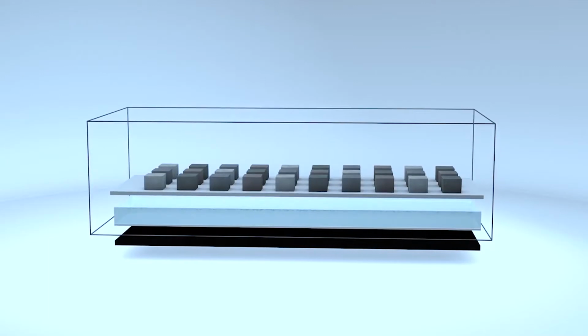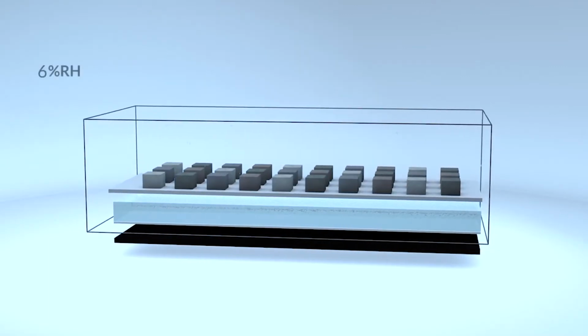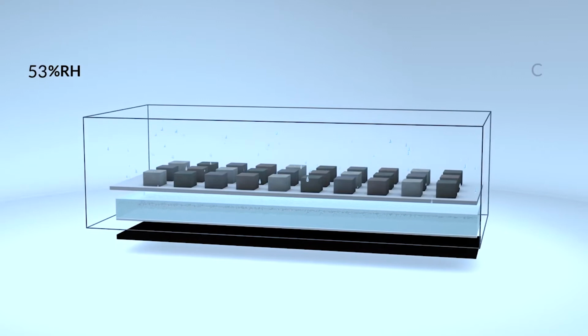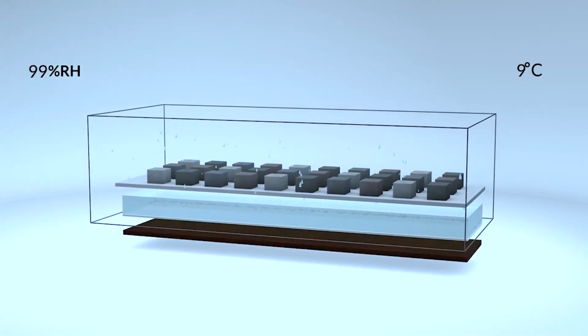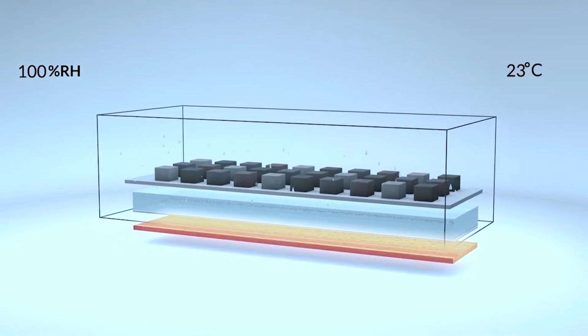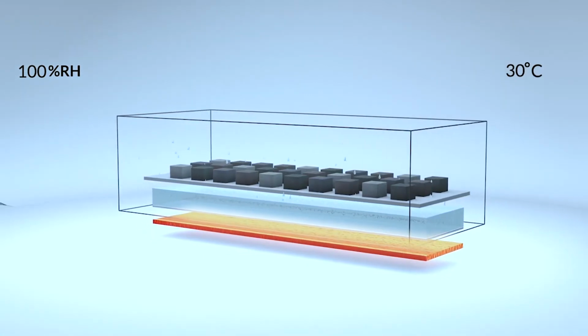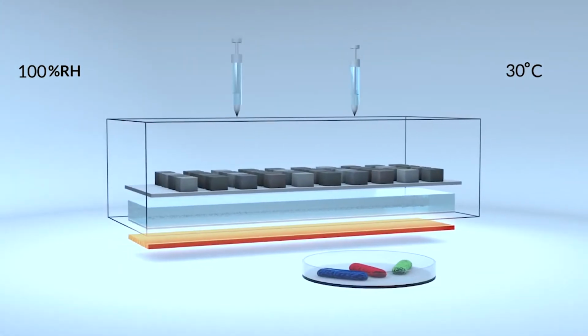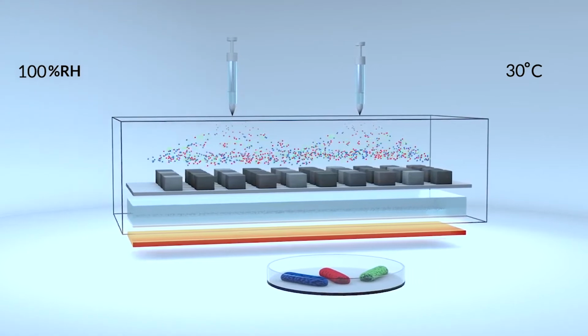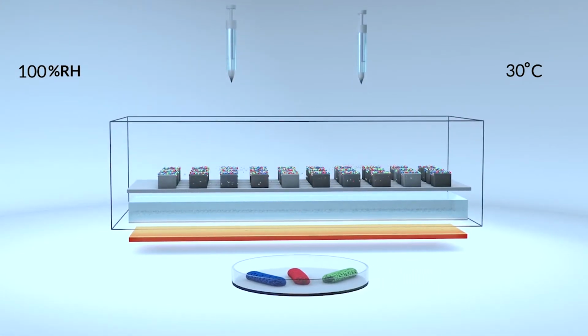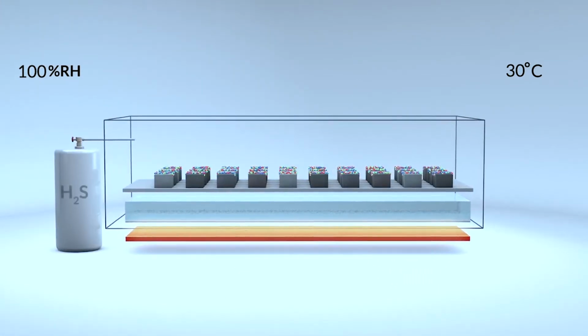The test principle is simple. Specimens are put into an environmental chamber. The air is saturated with moisture and the temperature is increased to 30 degrees C. Then bacteria typical of sewers are introduced. H2S is fed around 50 parts per million alongside bacteria nutrients.